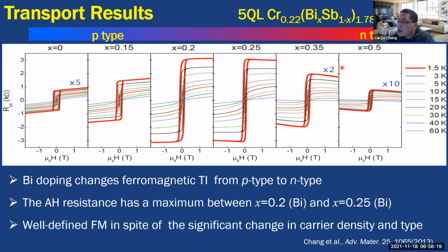And we can see that when you tune the carrier density and the carrier type, the ferromagnetic property is always there. It doesn't look like the diluted magnetic semiconductor, where the ferromagnetic property can only be realized in the p-doped regime. So here actually tells us the ferromagnetic property can survive in the insulating regime. This is good news for the quantum anomalous Hall effect. And we can see the anomalous Hall resistance actually increases in the insulating regime. Here it is just 3 kilo ohm, still far from the quantized value. You know, our goal is h over e squared, the Hall resistance of 25.8 kilo ohms.